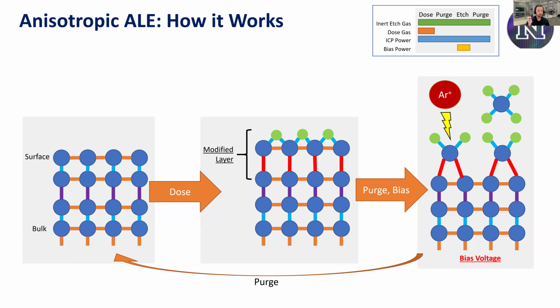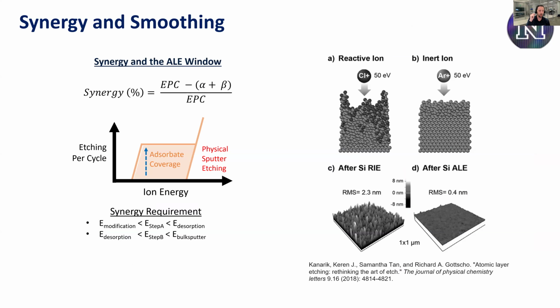The way that we think about this process from a figure of merit point of view is something called synergy. In synergy, we think about the etch per cycle. How much did we remove with each of these cycles? And then let's subtract out what happens if we just run the dose step over and over again. That's alpha. What happens if we just run that etch step with no chemistry, no modification, over and over again? That's beta. So how much are those steps contributing? And then we really look for synergies that are in excess of about 90%.